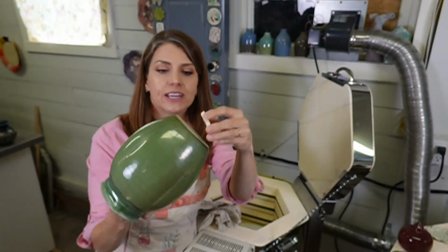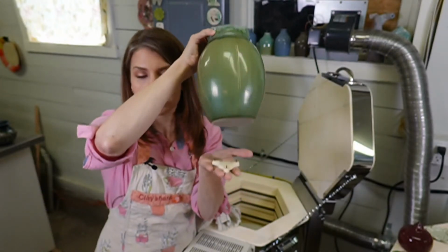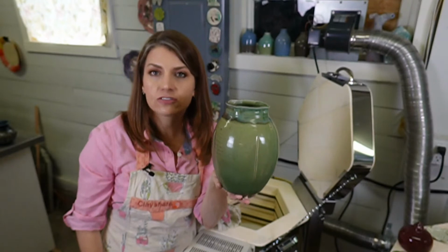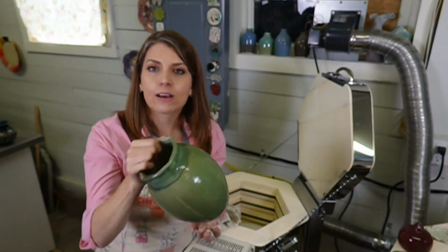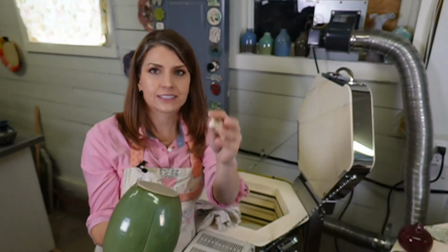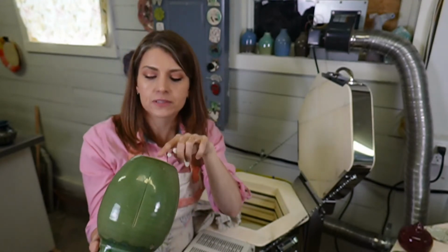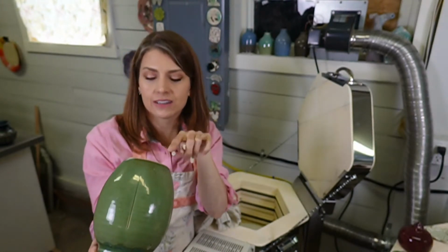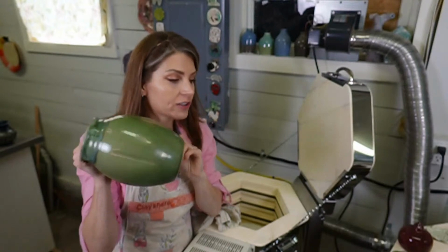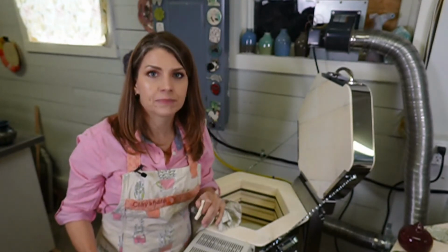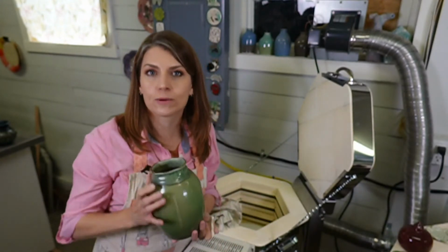So what you would do is sit it on one of these stilts here, and you would just glaze fire your mug like this, and then when it's done, you might have three, because this has 3 points, 3 little bumps. Sand them down with a little sanding pad, and they're fine. So that's what you do to make all your earthenware food safe. Just glaze both sides, and that's the same with earthenware plates. You can stilt earthenware plates and fire them. The reason they don't warp is because they don't get to those hot temperatures that cause them to warp. I've got a ton of pots out now.